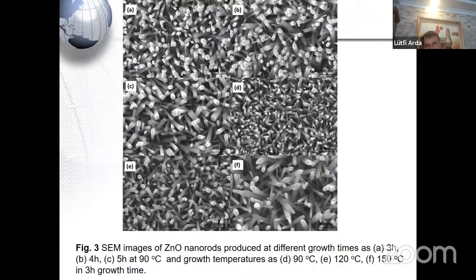As is well known, zinc oxide consists of polar and non-polar crystal planes, which affect the growth habit of its one-dimensional nanostructures, such as nanorods. Also, we can conclude that temperature has a strong effect on the axial and lateral growth rate of crystal planes. The difference in the growth velocity between these polar and non-polar planes could be responsible for the pyramid-like structure.